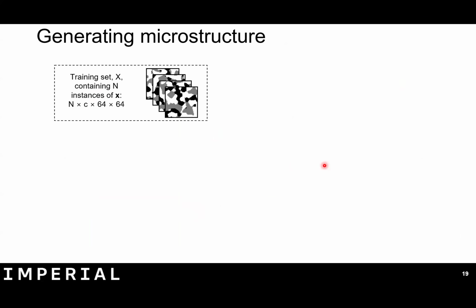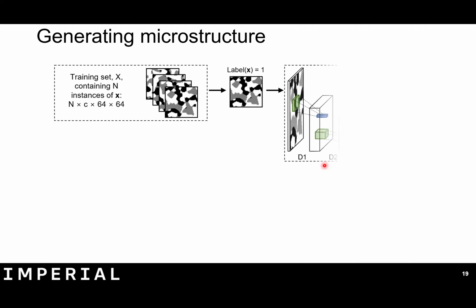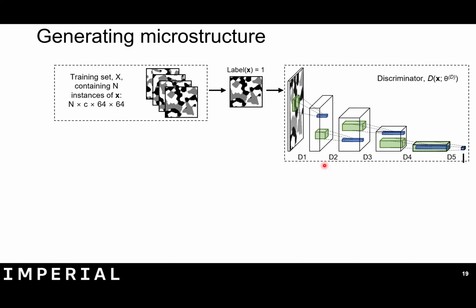So once you've imaged your data, you've segmented it, and you've checked for representativity, next, certainly for our team, we wanted to try and understand if we could learn the core underlying statistics of that image. And so about 5 years ago, we started playing with generative adversarial networks. This is where you get two deep convolutional neural networks to compete with each other. One network takes in little patches of your segmented image, and it's trying to give them a high score. It's trying to say, in comes an image, and I want the output to be a high number to show that I believe it's from the training set.